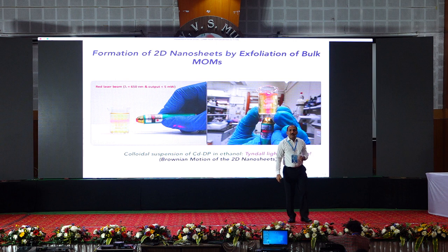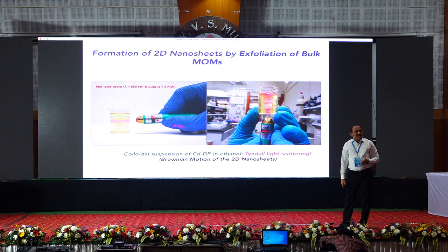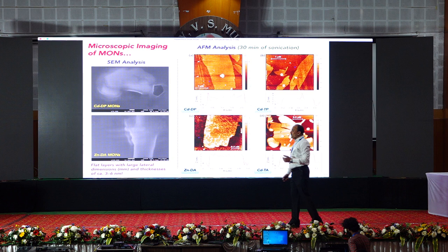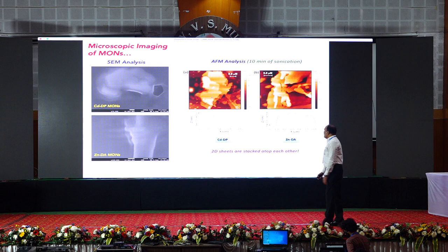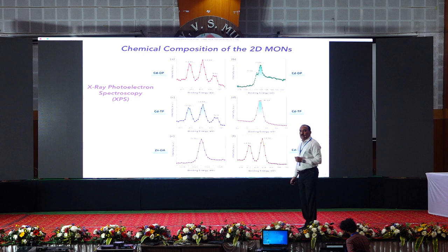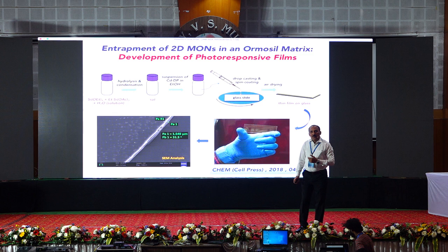And how do you know they are two-dimensional metal organic nanosheets? Of course, the Tyndall effect is one of them. And you can go after all kinds of experiments involving microscopy to show that they are 2D metal organic nanosheets, and show that ultrasonication doesn't destroy metal-ligand bonds, with XPS and everything you can do. And if you allow the material to come back again, it reforms, and you have the X-ray crystallographic signature.